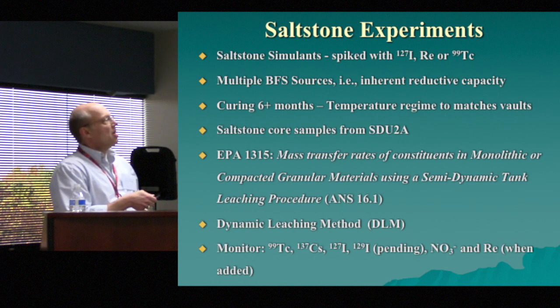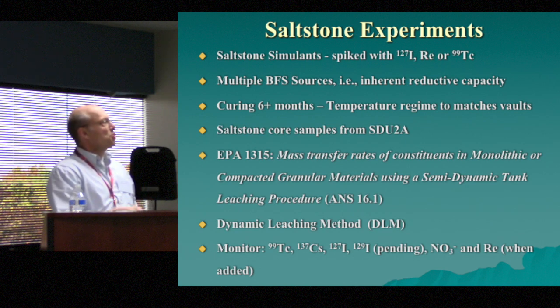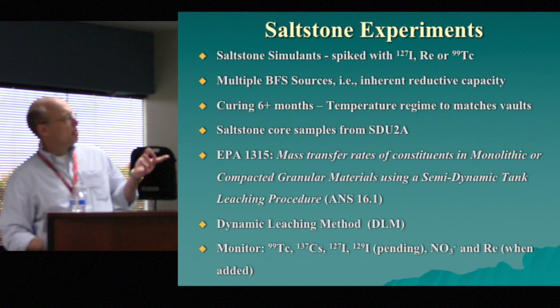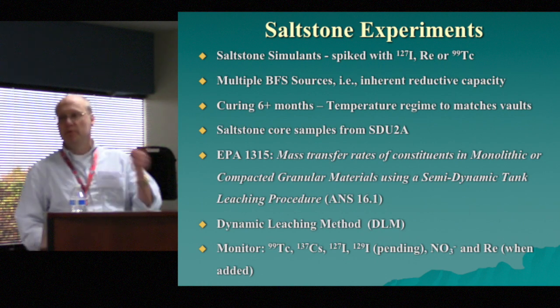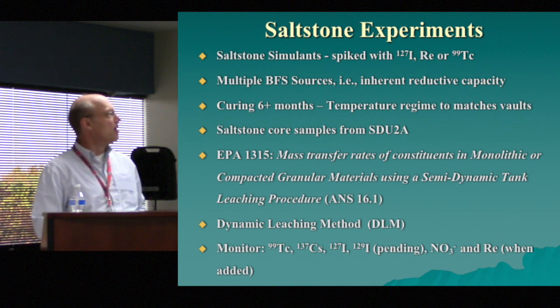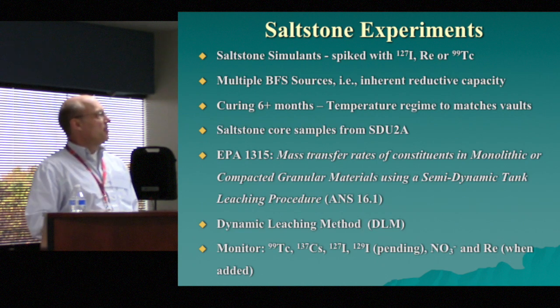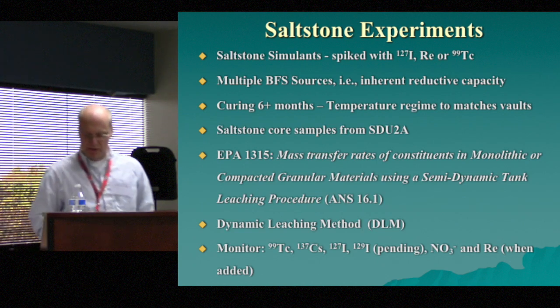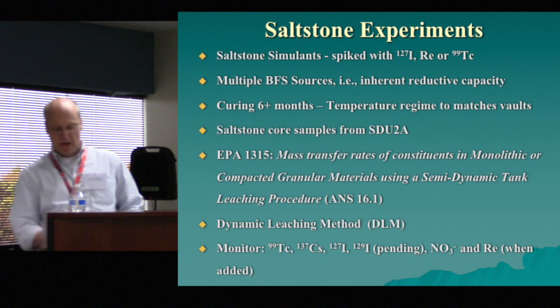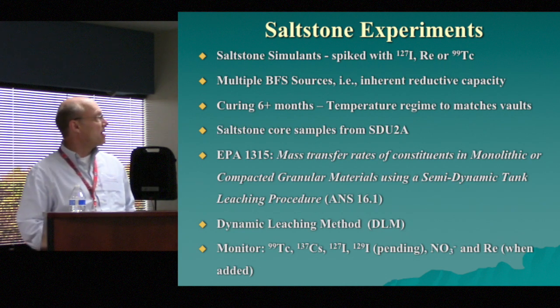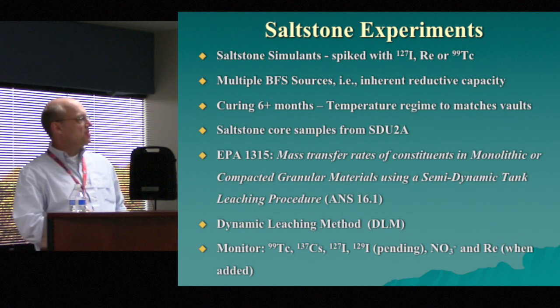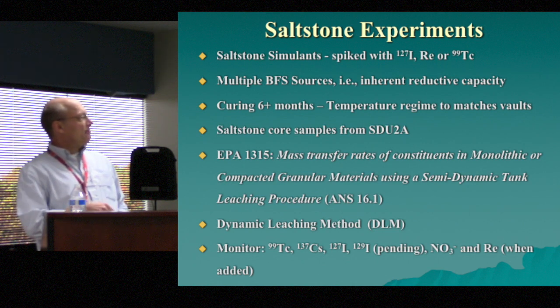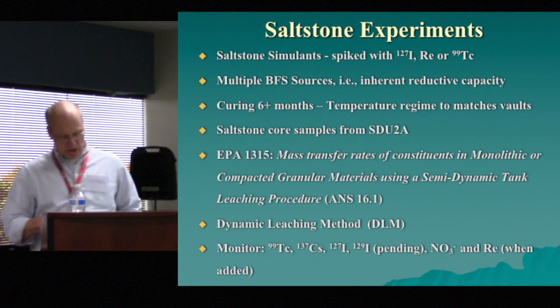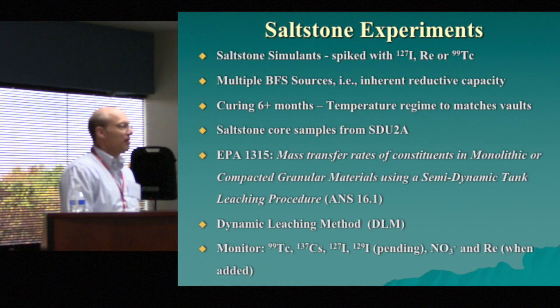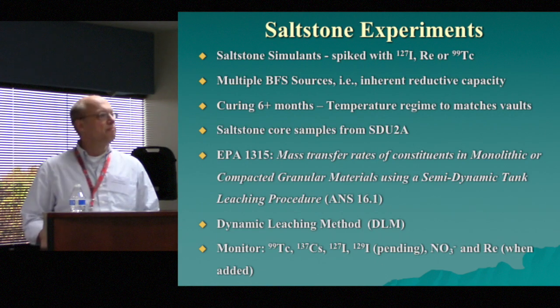So in addition to the actually simulated cores, we also have 3 samples of the SDU2A samples that Steve was talking about earlier. Now we did the EPA 1315 mass transfer test that was developed at Vanderbilt University by Dr. Kosson's group, which is very similar to the ANS 16.1. And then finally, I want to talk about this dynamic leaching procedure method that we're developing here at the SRS. Next slide.